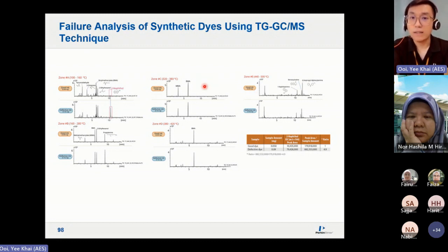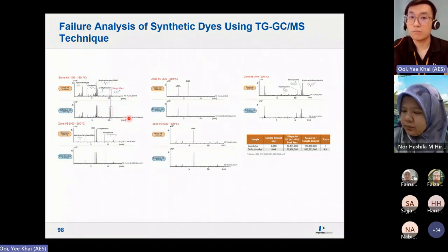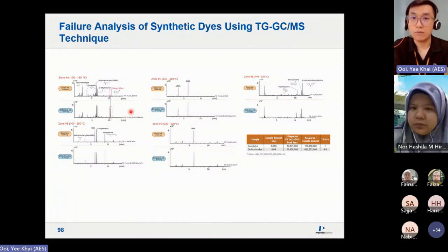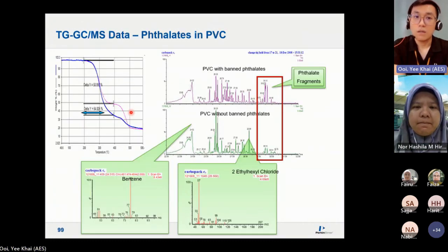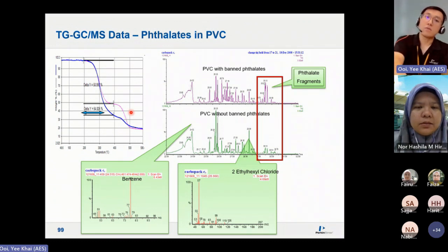As for other decomposition, you can see different regions of decomposition coming from TGA, but the other regions all match well except the first, which means they added in a lot of maybe a plasticizer or additives into the defective ink. Then we can use TGGCMS to check the phthalates in PVC as well.